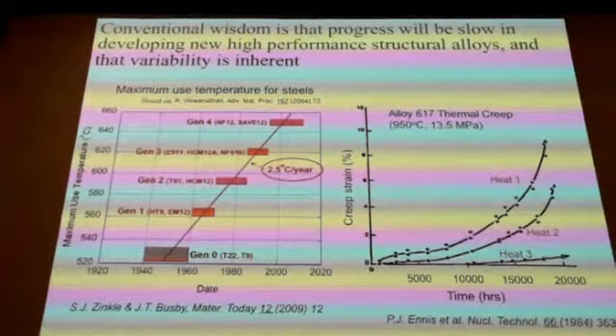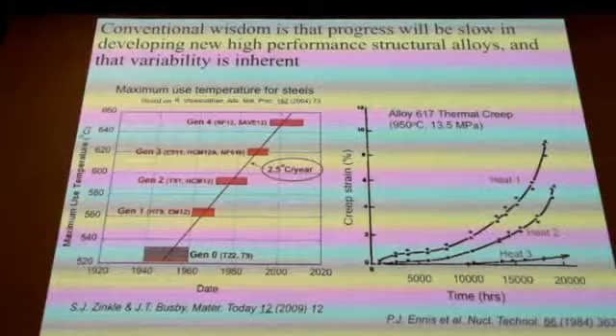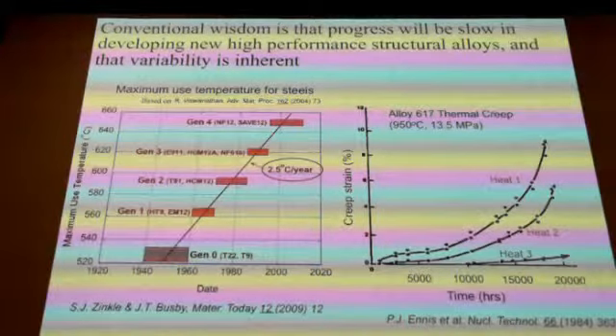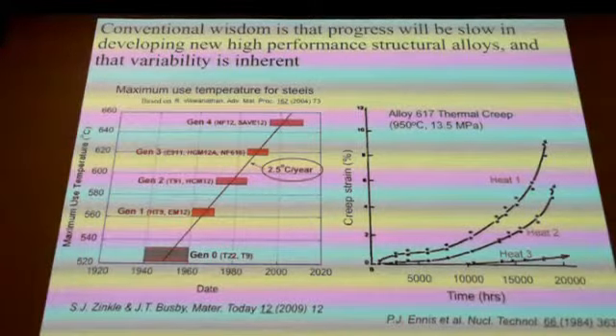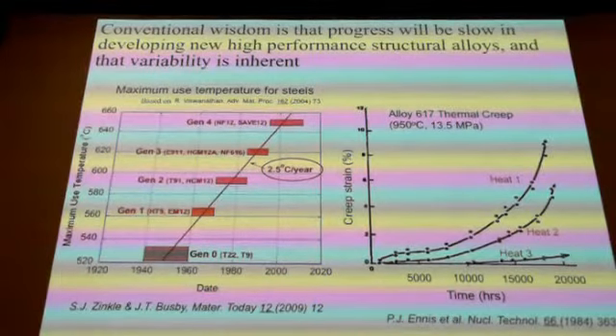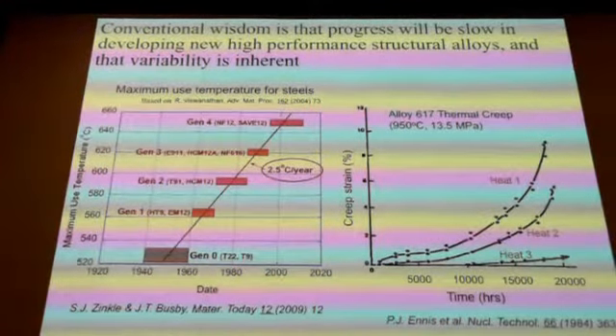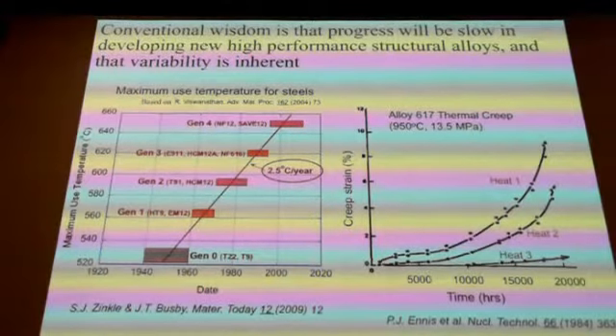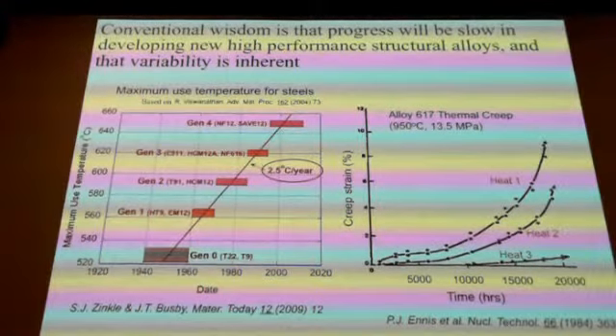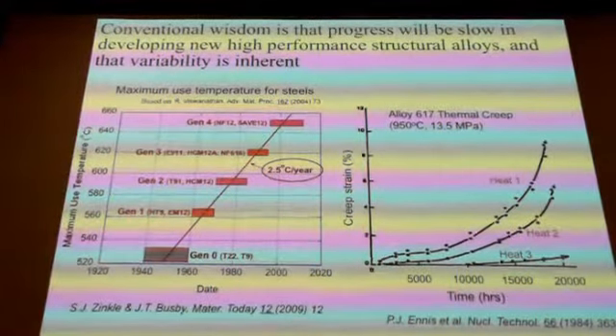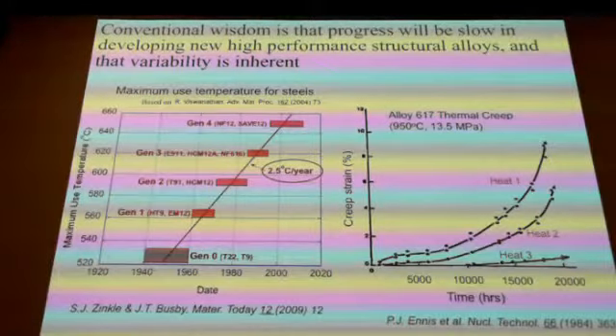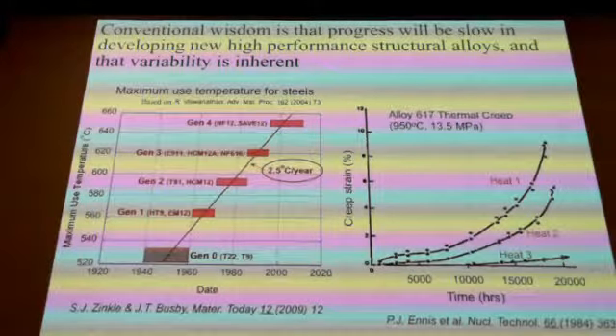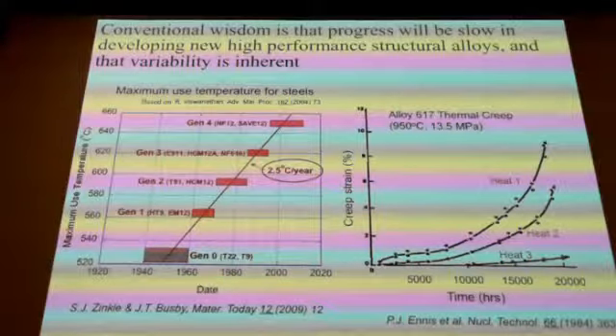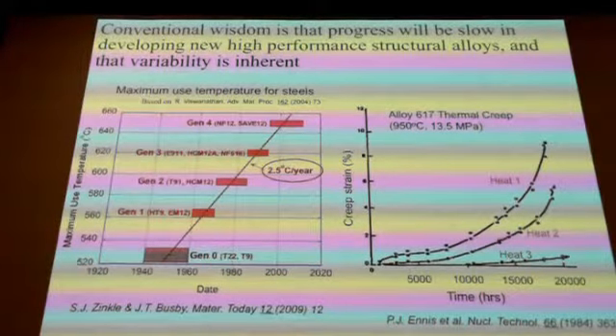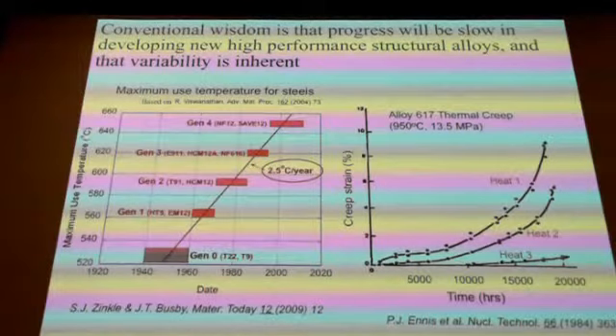So in the last couple of minutes, I'll just quickly go through how we can use some emerging or currently available materials science techniques to try to develop high performance materials. I'm showing in the left plot the historical record for coming up with steels with ever increasing upper use temperature as a function of the date that the steel was introduced. You get this nice linear relationship. Unfortunately, the slope of this is only 2.5 degrees centigrade per year, so we're steady and slow in our progress.